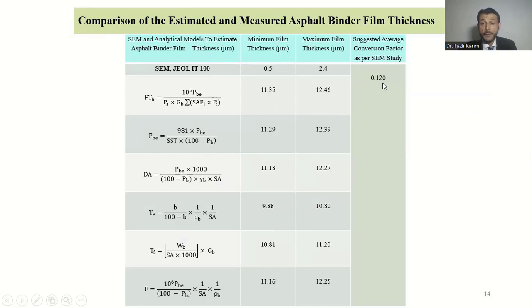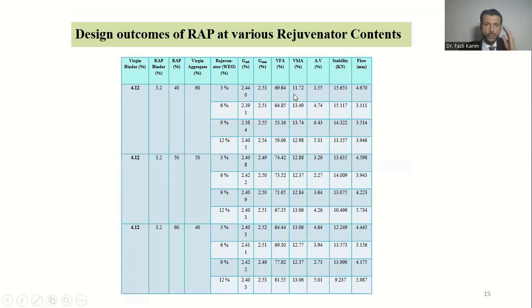Therefore, a statistical factor, a transformation factor, was developed so that the analytically assessed values can be transformed into the range of film thickness measured during micro level techniques. The next phase was basically to measure binder film thickness in the recycled mixture.